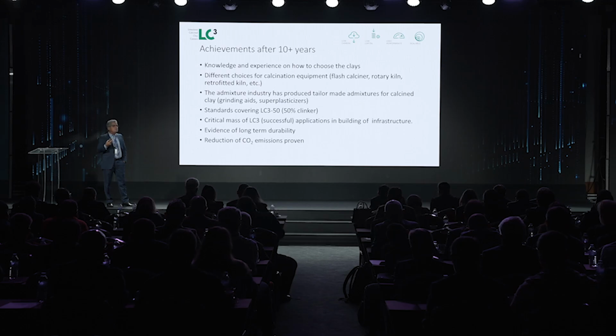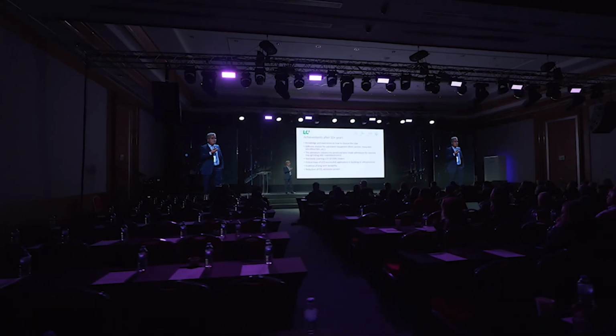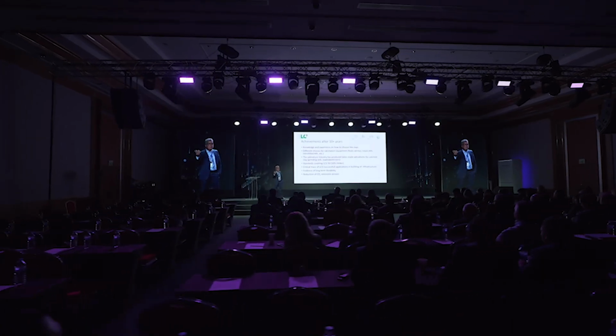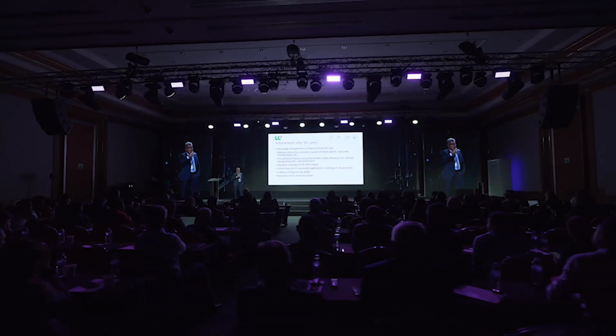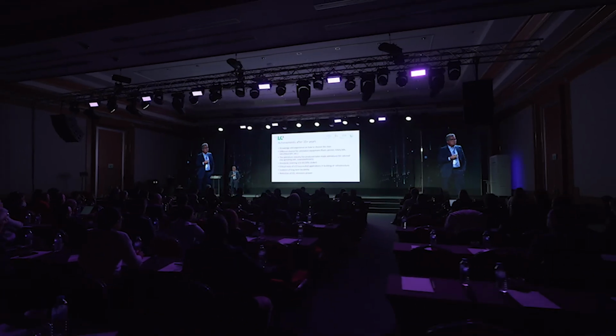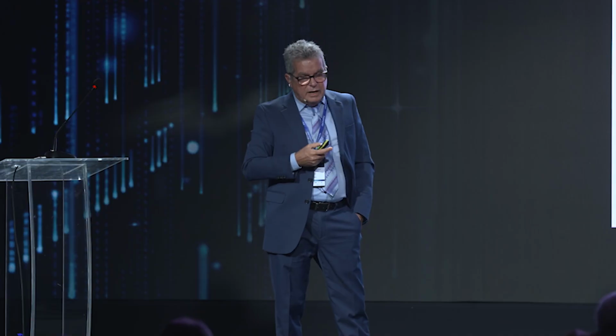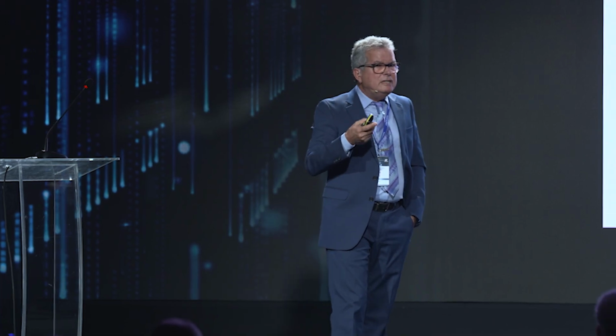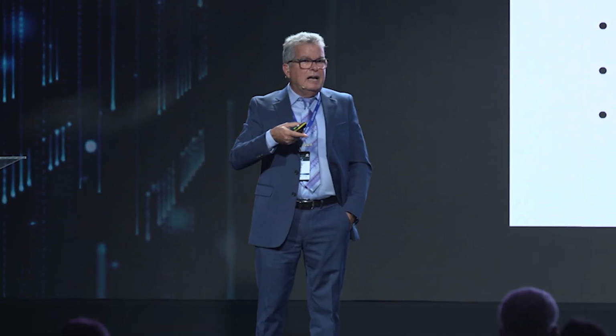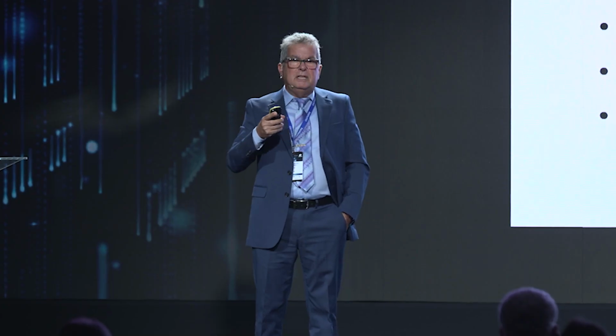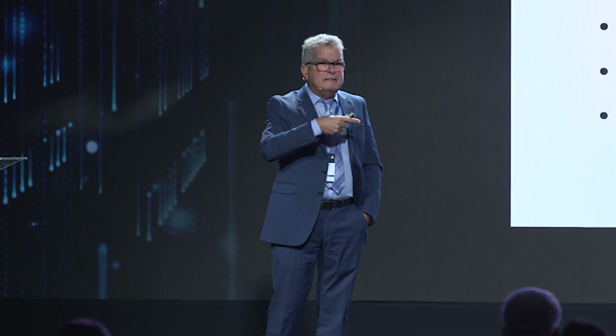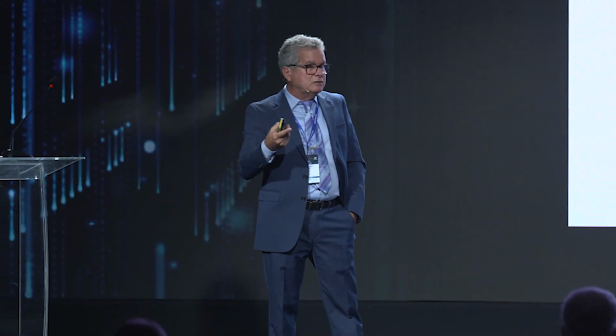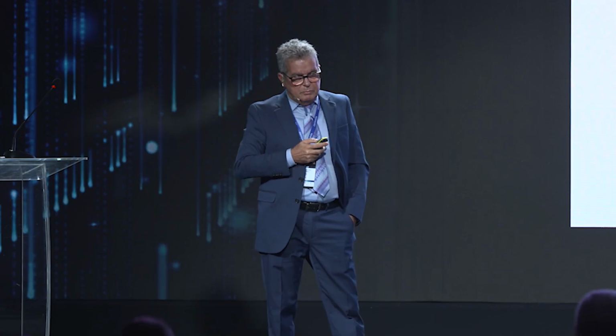We have different choices. Machinery producers: today we have more than 9 companies offering equipment for clay calcination. Some of them are here in the fair, and they have stands, but it's no longer a problem to have access to suitable machinery for clay calcination and also for grinding the clays. The admixture industry, which is also represented here, has done a lot of work. 8 years ago, using plasticizers in concrete with calcined clays was a challenge because of the high water demand. Today, there are products that resolve this problem, and it is no problem at all.